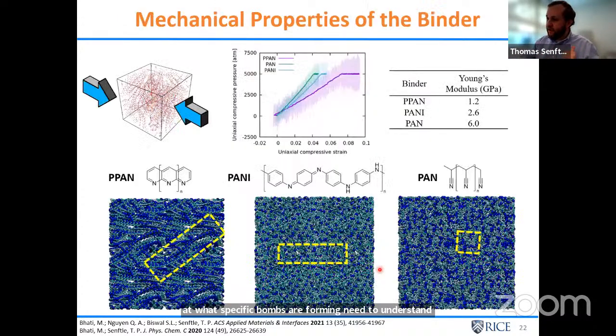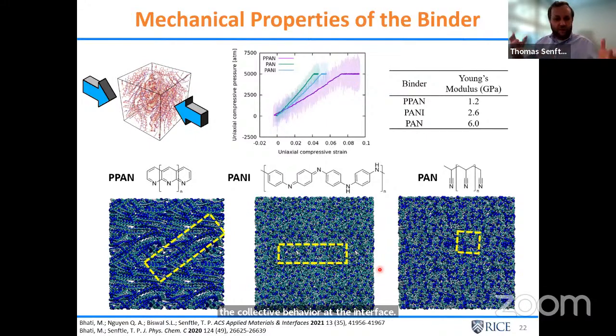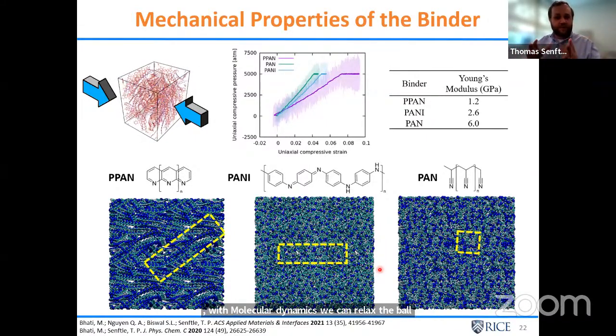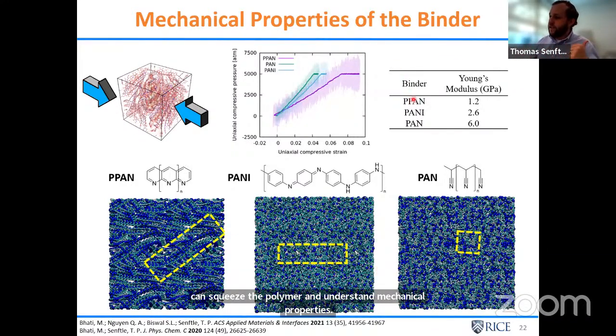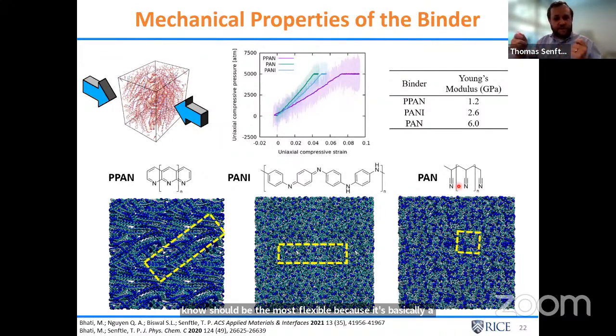So other properties that we looked at, of course, with molecular dynamics, we can relax the bulk and we can squeeze the polymer and understand its mechanical properties. So here we found that the p-pan has the lowest Young's modulus. It's the most elastic. And again, this is a little bit counterintuitive. We would expect the chains of p-pan to be the least flexible because you have these aromatic rings, right? The pan should be the most flexible because it's basically a chain that can spool itself up.